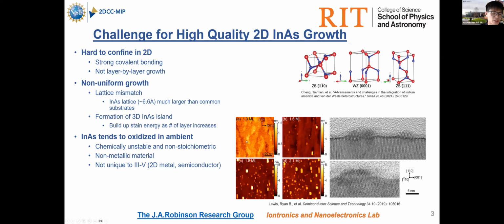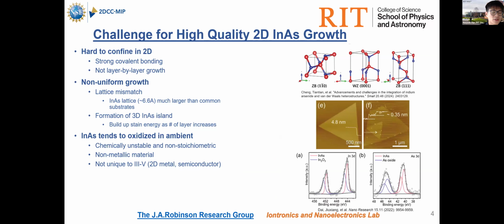From this literature, in an AFM image, as the layer number increases, you gradually see a higher density of 3D indium arsenide islands shown as the bright spots. And here's an SEM image showing the cross section. So that's the second challenge. And the third one is, even though people have successfully grown thin film indium arsenide, such material, similar to other 2D metals or semiconductors, is really easy to oxidize. Even though they achieved a layer of 0.35 nanometer, which is a monolayer, it does have significant indium oxide and arsenic oxide peaks in the XPS data.